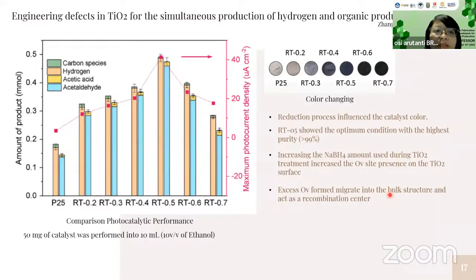And how about the photocatalytic activity? We can also see that by increasing the sodium borohydride concentration, the hydrogen production also increased. And 0.5 is the optimum condition to produce hydrogen with a purity above 99%. Then when we added more sodium borohydride, the hydrogen production decreased. It was due to the excess oxygen vacancies migrating into the bulk structure and acting as recombination centers. So in this case, we should find the optimum number of oxygen vacancies to get the optimum hydrogen production.